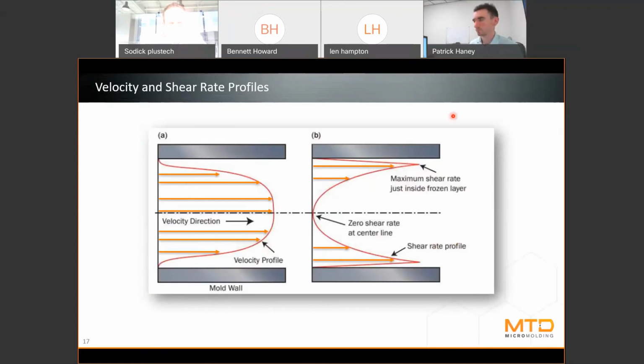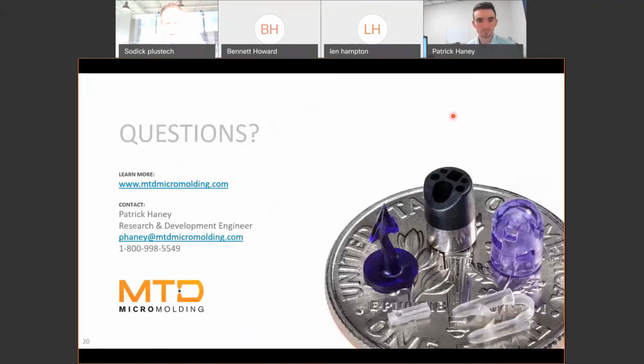Excellent. Do you monitor and adjust the nozzle orifice size per resin to minimize or optimize shear rates and the inherent variability that occurs between the nozzle and sprue bushing, including tip breakage?